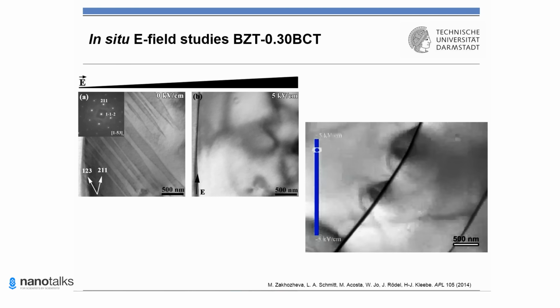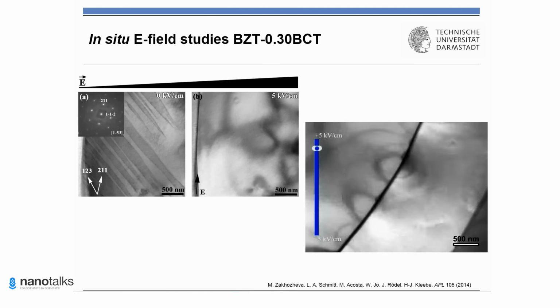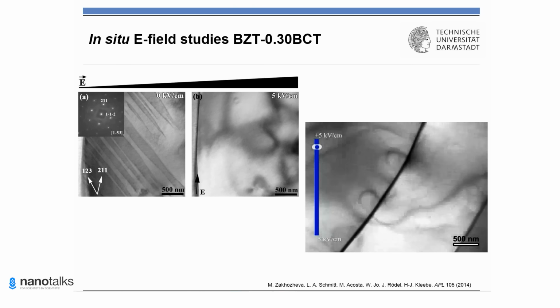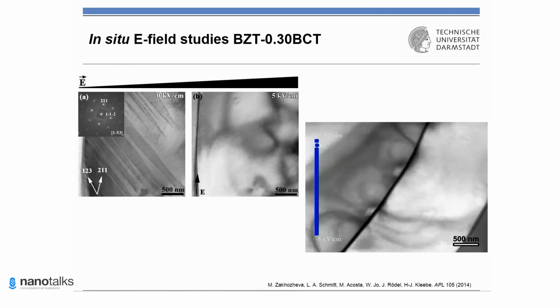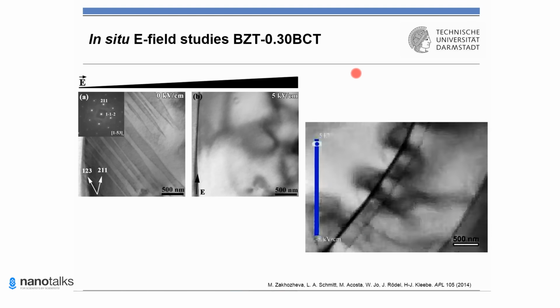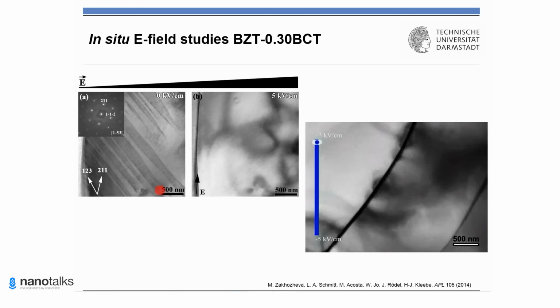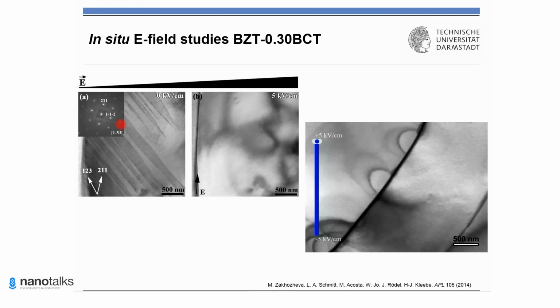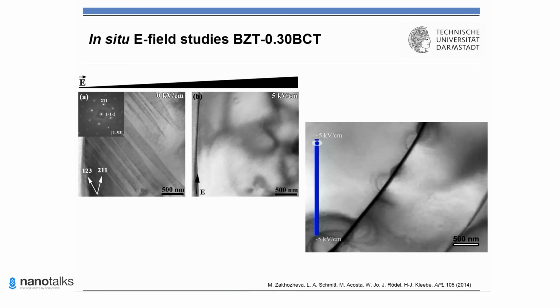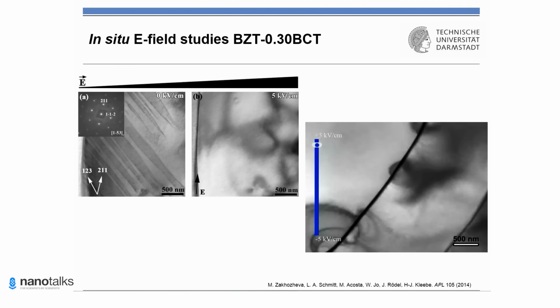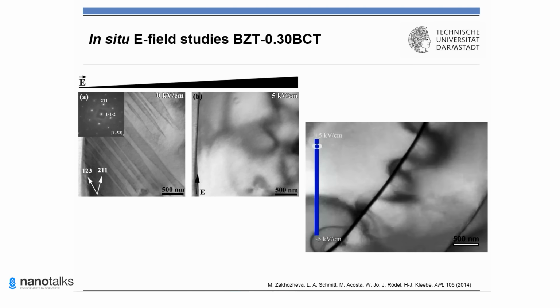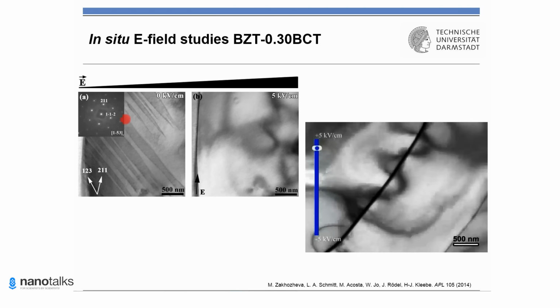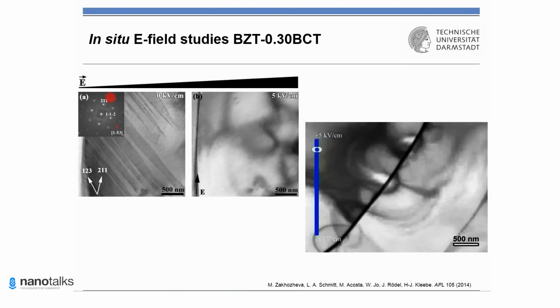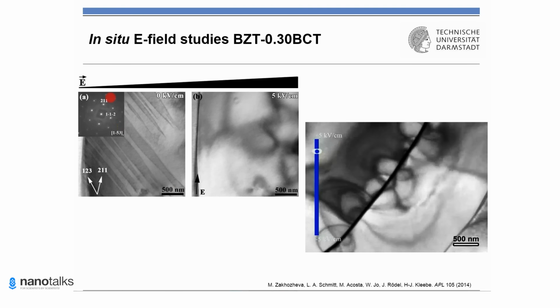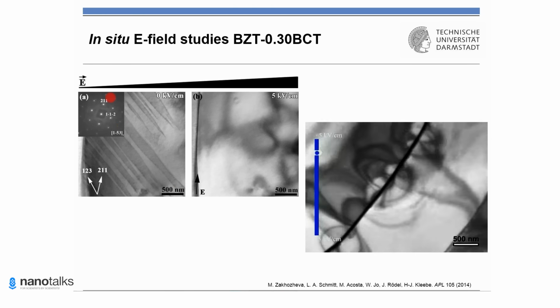So why are domains critical for ferroelectrics? Well, what actually are ferroelectric domains? Ferroelectric domains are regions within the grains, like here, which exhibit a uniform polarization. And piezoelectric ceramics are characterized by very well-defined domain walls, which are critical for dielectric, piezoelectric, and ferroelectric